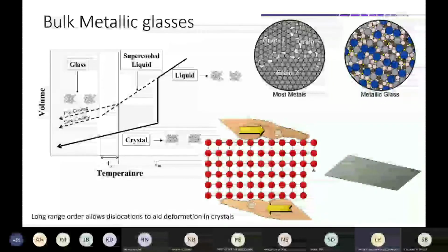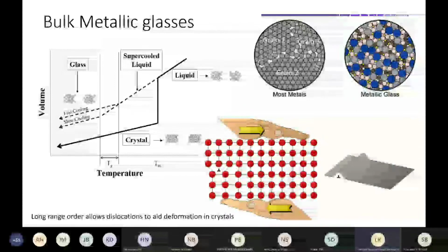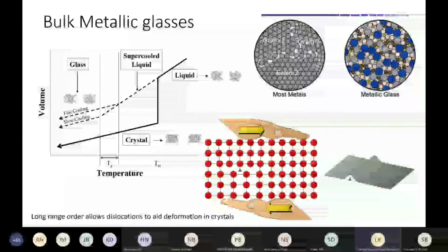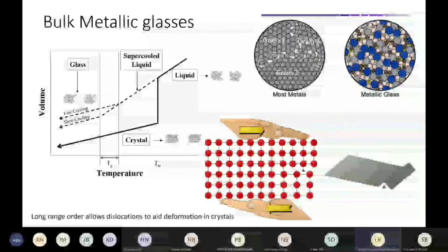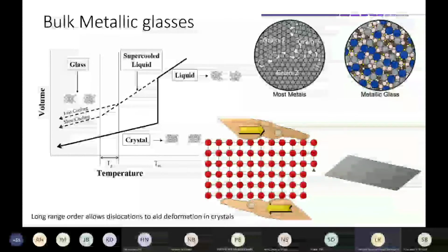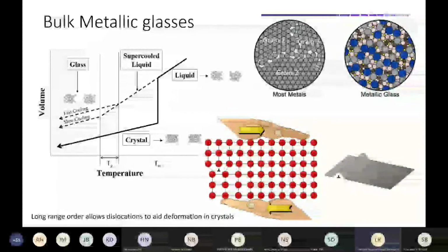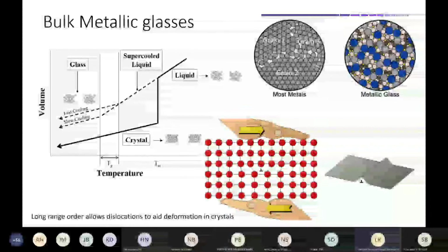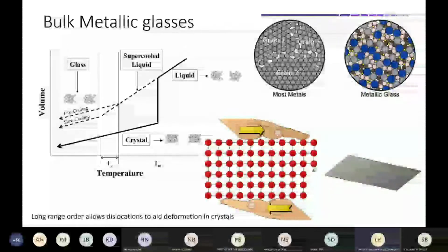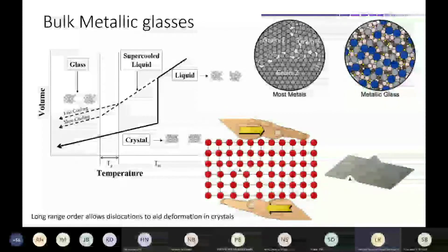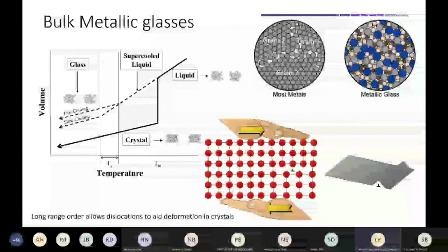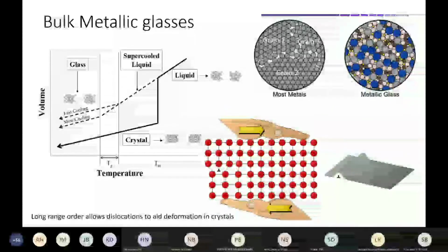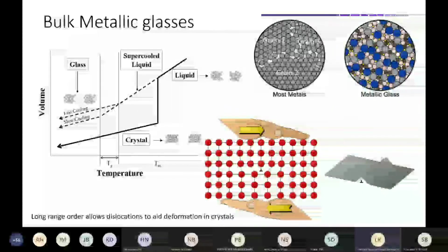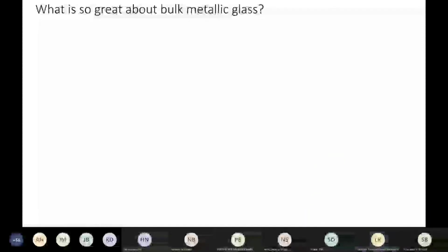But you cannot define such a thing in metallic glasses, because you can obviously see here we can define a crystallographic plane over which this dislocation is sliding, and there are identical bonds above the half plane and below the half plane. So you essentially have the same environment, and there is no net energy loss when this dislocation moves from one end to the other, right? You're always preserving the number of bonds. But in a metallic glass, you can never achieve that, right? You cannot define a dislocation.